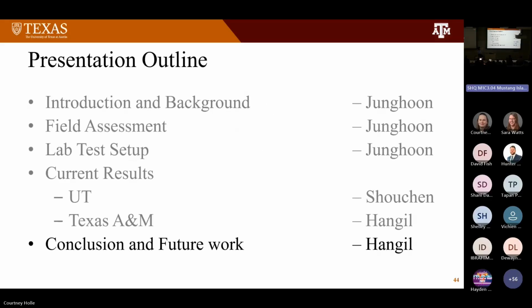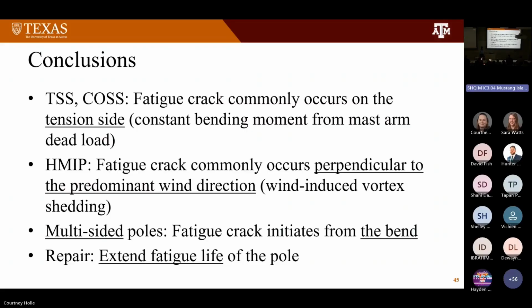So far, I presented the test results, and let me present the conclusion and future work from now on. This is the conclusion that we've got for the last 2 years of the project. From the field assessment, we found that traffic signal poles and COSS structures commonly have their fatigue cracks on the tension side. For the HMIP, we found that fatigue cracks commonly occur perpendicular to the predominant wind direction. From experimental tests, we found that multi-sided poles have their fatigue cracks initiated from the bend, and we also confirmed that repair can extend the fatigue life of the pole.